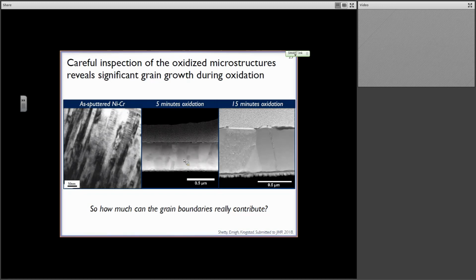The grain microstructure is fully equiaxed here. There's no evidence of this columnar nanocrystalline structure anymore. If we go for a full 15 minutes, we've already established this coarse-grained bamboo-like structure in our thin films. So really, how much can this nanocrystalline idea actually be playing a role? It must be doing something because we can see the evidence. But is it really the nanocrystalline behavior?